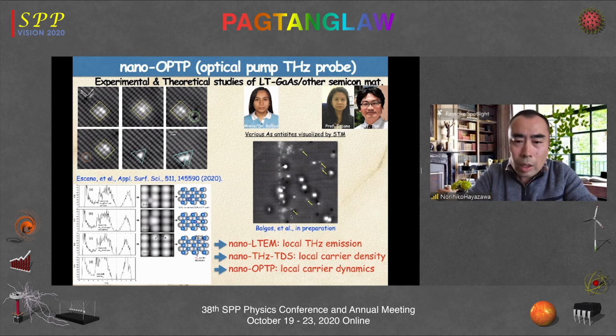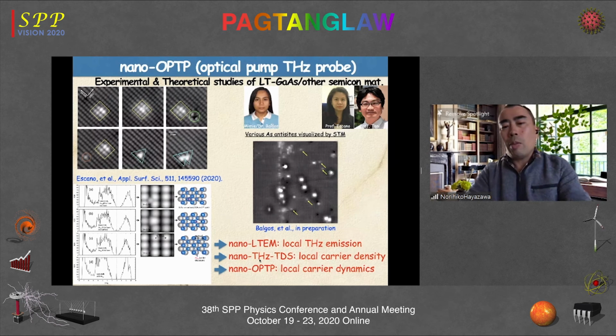Anyway, based on this experimental observation, as a summary, what we are expecting by using nanoscale OPTP is, at first, by using nanoscale LTEM, we will try to characterize the local terahertz emission from the local volume around the interface, also around the defect found in the STM image. Also, by using nanoscale terahertz time domain spectroscopy, we are expecting to characterize the local carrier density by this technique.